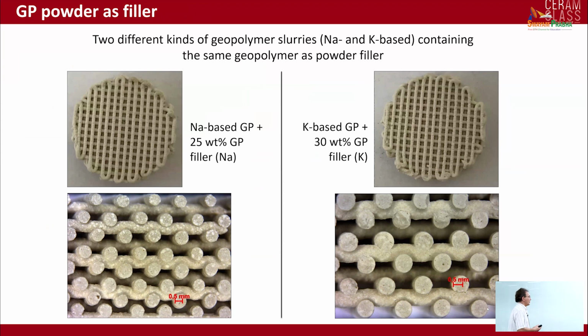So we developed an approach where we generated geopolymer particles with the same composition as the surrounding matrix. And since they were solid, they contributed to the optimization of the rheology of the slurry. Of course, we can do that with both sodium-based or potassium-based materials. You can see the particles here more clearly. And this allows a very good retention of the shape of the scaffold. So these were our early experiments.